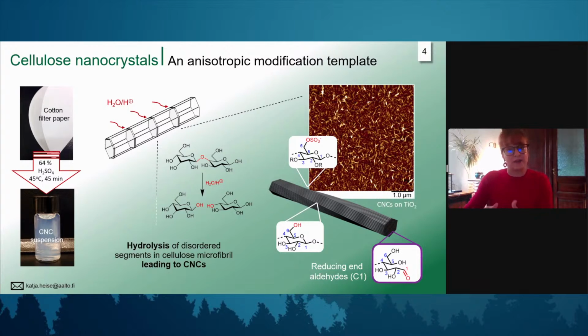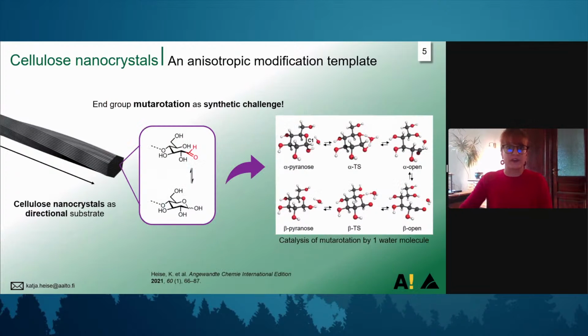Due to the biosynthesis of the cellulose, all chains are synthesized in the same direction, which results in all reducing end groups pointing towards one direction. And this enables Janus type modifications. So if we attach new functionalities to the reducing end groups, we end up with Janus type particles. And this all sounds very simple. So we have anisotropic particles, we have an inherent directionality of our cellulose nanocrystals, but we have significant, major synthetic and also analytical challenges.